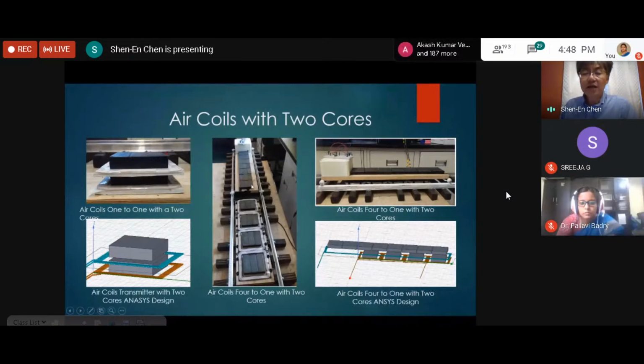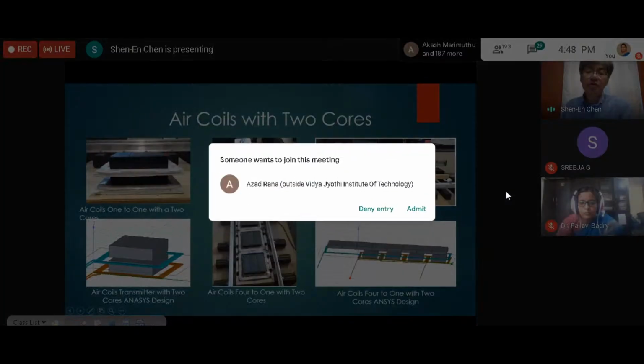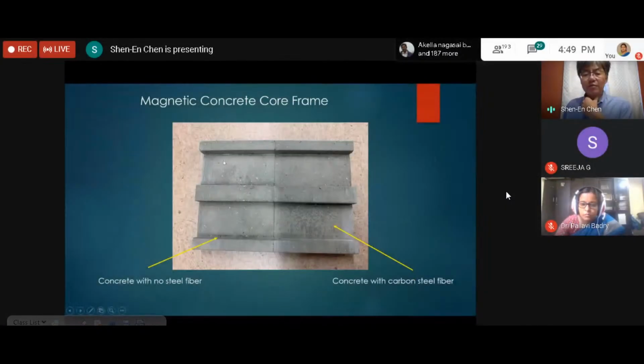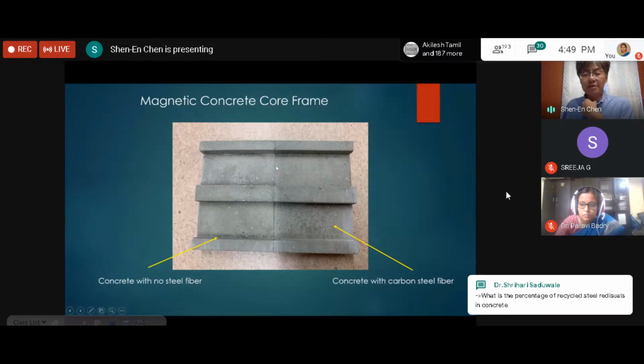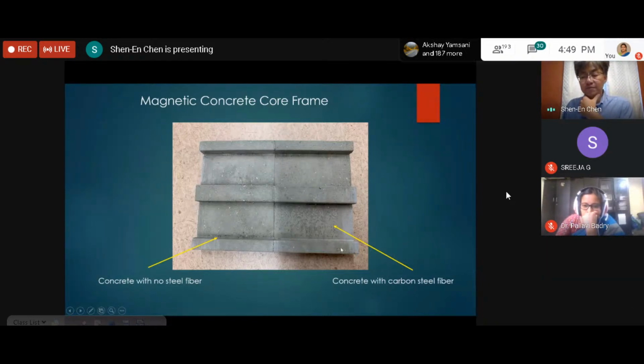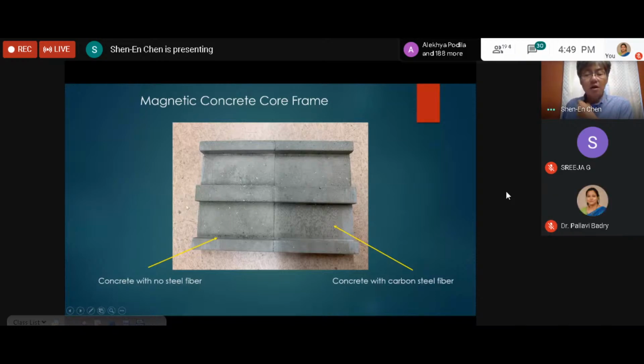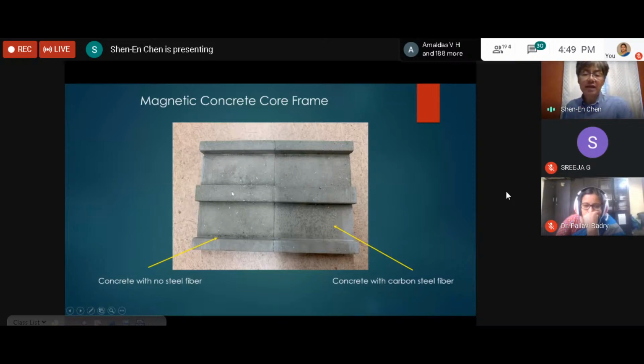But one of the challenges of this design is that these ferrite materials are very, very expensive, and they are very brittle, so they're not a very reliable element. So in our laboratory, we started to develop our own core elements using concrete. This is the regular concrete with no steel fibers, and this is the carbon steel concrete with fibers. Concrete without fibers would behave just like wood or air. Actually maybe slightly better because you do have some voids and moisture in it, but the one with the steel fiber embedded would actually perform very, very well.